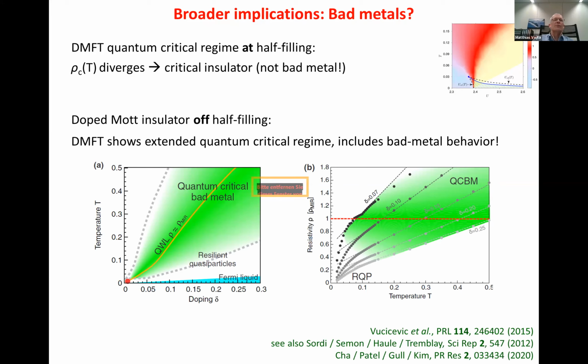The green regime is one which has been called bad metal here. You see this on the right-hand graph, which shows the resistivity as a function of temperature for different doping levels. In this green regime, which exists at elevated temperatures, the resistivity varies approximately linear with temperature, plus some offset, which is one of the hallmarks of the bad metal regime.